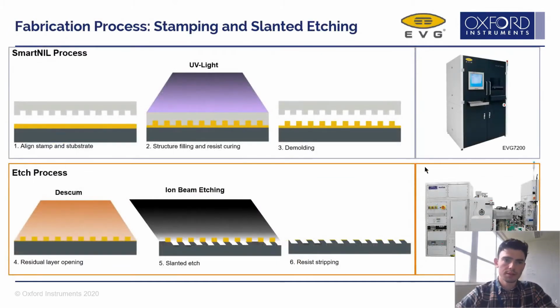So let's summarize that fabrication process. So a nanoimprint process by someone like EVG, using one of their tools shown on the right, we can stamp our substrate, cure the resist, and demold it. And now we have our sacrificial resin layer ready to be used as a mask. Now, using something like the ion fab from Oxford Instruments, we can descum the film and open up the mask. Use the etching to get our slanted etch or whatever geometry we're trying to achieve, and then strip off the resist for our final product.